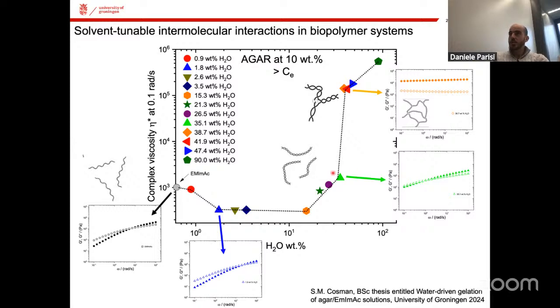However, when we shift the content of water between 30 and 40%, there is a huge shift in viscosity. We are talking about 2 orders of magnitude of difference in viscosity, because all these double helices start forming cross-linking points. So they basically form a network. And as you can see from this rheology plot, the storage modulus is always much higher than the viscous modulus, suggesting a strong viscoelastic solid, namely a gel. So the condition here is that the initial polymer concentration must be higher than the entanglement concentration, meaning that in dry conditions, the agarose chains should form entanglements.